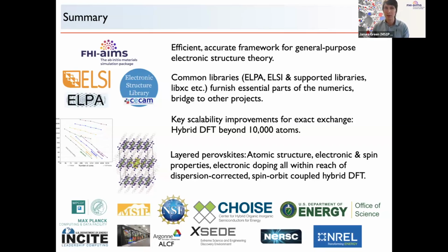Can you talk about the use of dielectric dependent hybrids for 2D or 3D perovskites? I cannot say much about dielectric dependent hybrids because we have not tried them. I think the impact for 2D and 3D perovskites would be better, but the key is again that the material is inhomogeneous, and you will have to have a degree of approximation in how you treat the organic versus the inorganic part. My personal bet for this, but that's the future, is to do something closer to maybe a local hybrid or real GW calculations if we get there. That would be nice, because then I think the screening is captured correctly. But I cannot say anything specific about dielectric dependent hybrids because I haven't tried them.